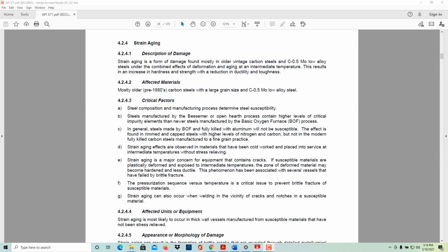4.2.4, strain aging. Strain aging is a form of damage mostly found in older vintage carbon steels and carbon half-moly low alloy steels, under the combined effects of deformation and aging at an intermediate temperature. This results in an increase in hardness and strength with reduction in ductility and toughness. Affected materials are mostly older pre-1980 carbon steels with a large grain size and carbon half-moly low alloy steels.